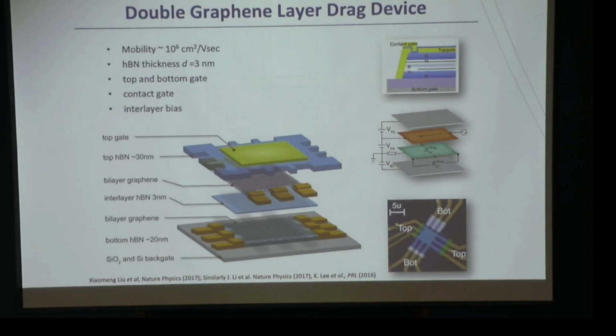What is the point of doing this experiment? The one important point is that the electron is now very strongly confined to graphene. We can put them together very close by, right? So we can actually increase the exciton binding energy quite high. That allows us to do these experiments not in the tens of millikelvin, but at 10 kelvin. Almost two or three orders of magnitude larger. Which allows us now to carefully map out the phase diagram of the exciton condensation.